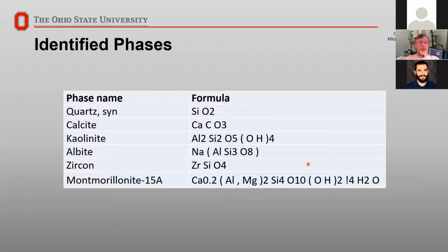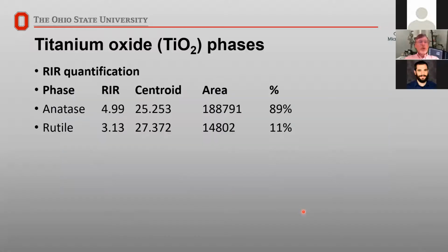Now, not only can we look at all these different minerals, but sometimes when you're looking at different phases, these have the same chemical composition. Titanium dioxide: 1 titanium, 2 oxygen. But it turns out that titanium dioxide can actually crystallize 3 different ways. You can have one crystal structure, which is called anatase, another crystal structure called rutile, and then there's a third crystal structure called brookite, which is generally less common.